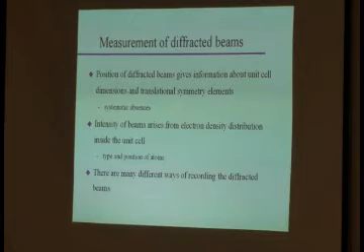In addition, we've established in handout 9 that the intensity of the beams is related to what type of atom sits where in the unit cell, because that is given by the structure factors, and those are the sum of all Fj, and Fj of course depends on the atom, times e to the i2π(hxj + kyj + lzj). So it depends on the position of the atom too.